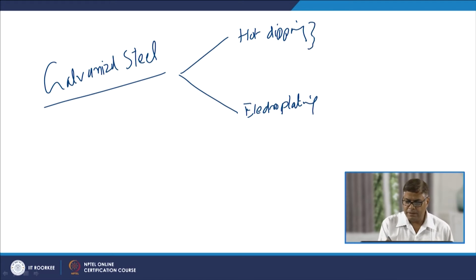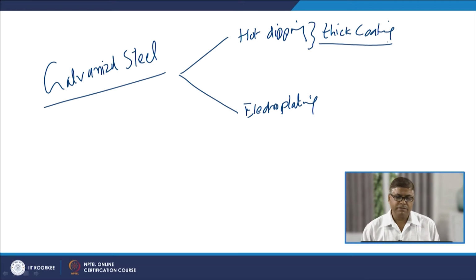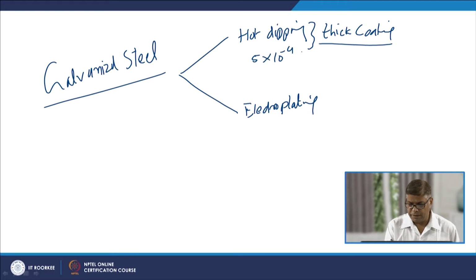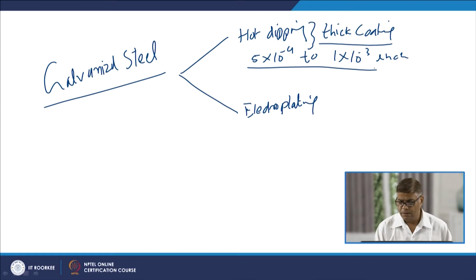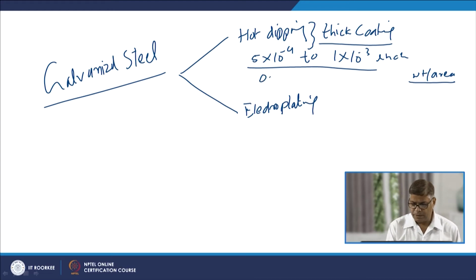Hot dipping method in general leads to the development of very thick coating, and if a larger amount of zinc is getting into the weld, it will be more problematic from the weldability point of view. The thickness with hot dipped galvanized steels ranges from 5 x 10^-4 to 1 x 10^-3 inch. On the other hand, the weight of zinc per unit area in galvanized steels produced by hot dipping ranges from 0.6 to 1.25 ounce per square feet.